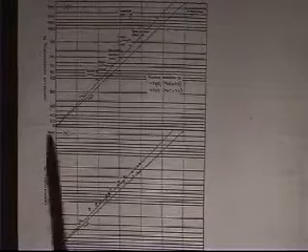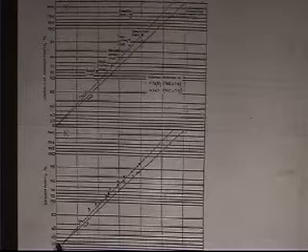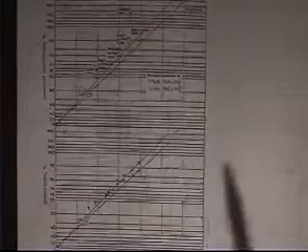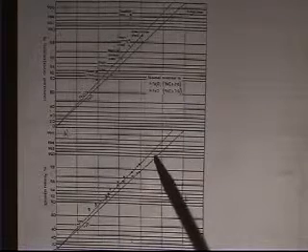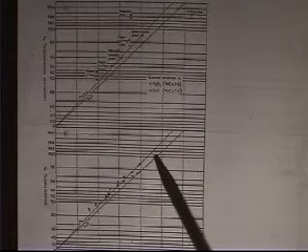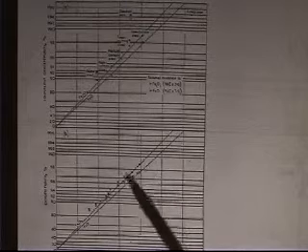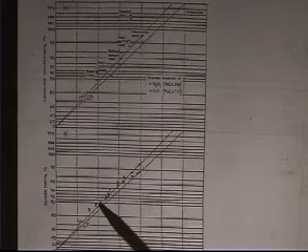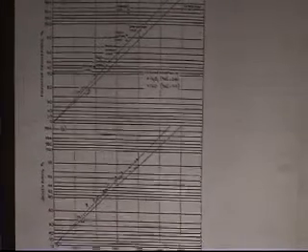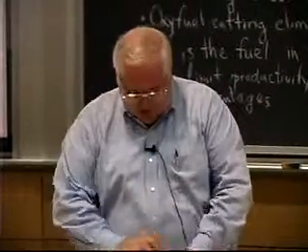He also called this equivalent oxygen purity. You can also add impurities like nitrogen to your oxygen, and if you're at 99%, you can get fairly high cutting rates. But as you drop down to 90%, you put 10% nitrogen in the oxygen, and you'll drop your cutting speed down by about half. In fact, he showed in his paper that 1% carbon had the same effect as 6.2% nitrogen, if you want to know precisely what that means.